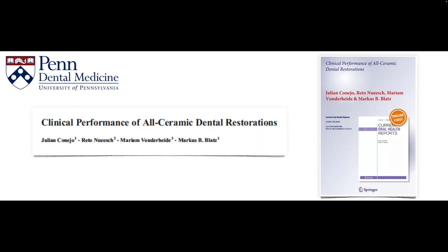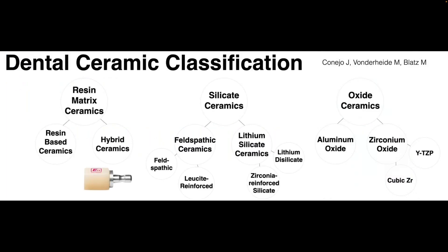With that quick introduction of what I try to have ready when thinking about chairside inlays and onlays, let's get to the material. Today we planned this webinar to talk about hybrid ceramics. The hybrid ceramic group is part of the big family called resin matrix ceramics. A hybrid ceramic is basically a porous feldspar porcelain block that is infiltrated with 14% composite — this reduces the brittleness that feldspar ceramics have and makes it smoother for machinability. Marginal adaptation on hybrid ceramic restorations is extremely good because the material has that composite component improving machinability.